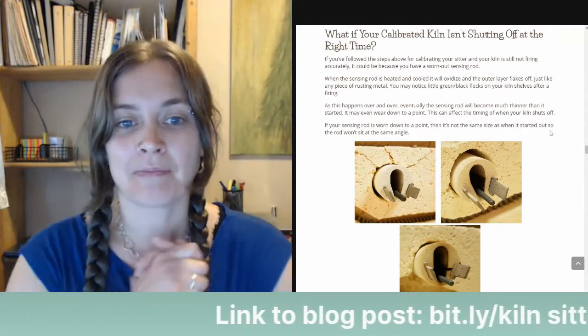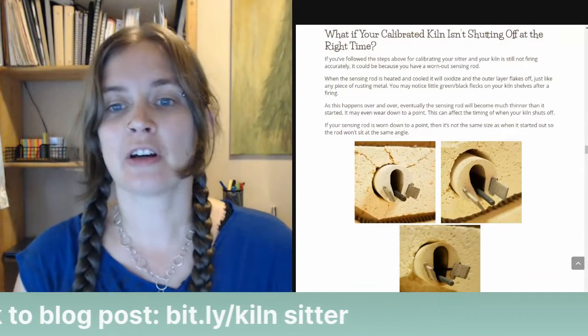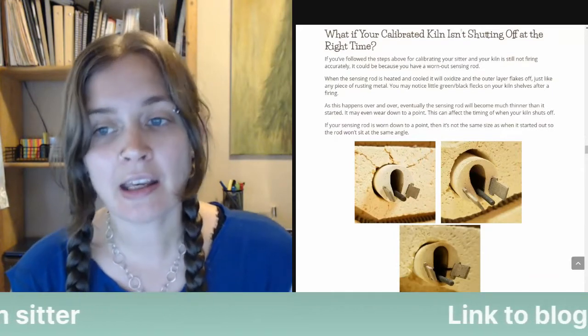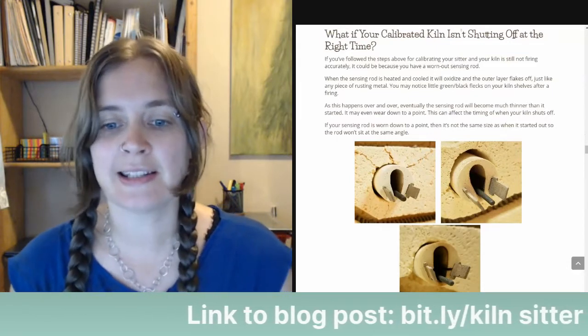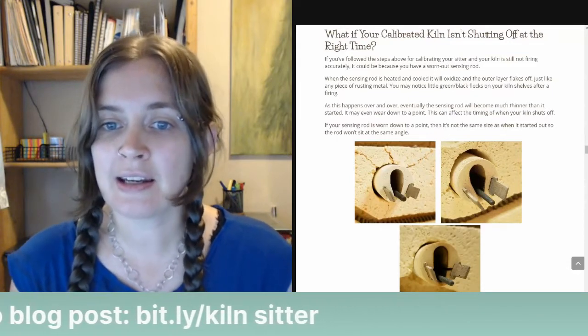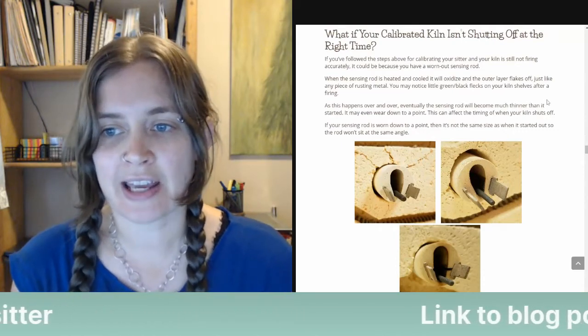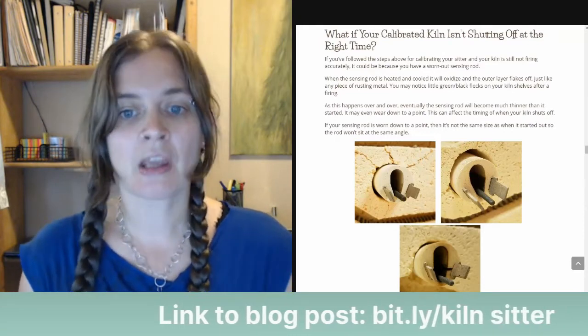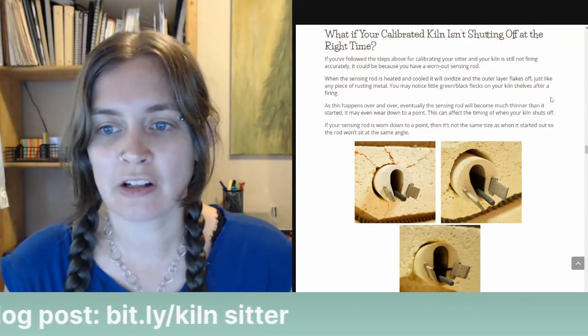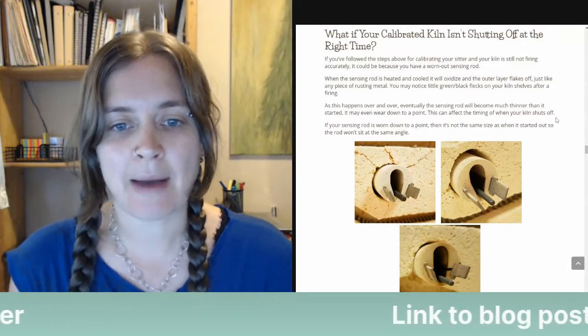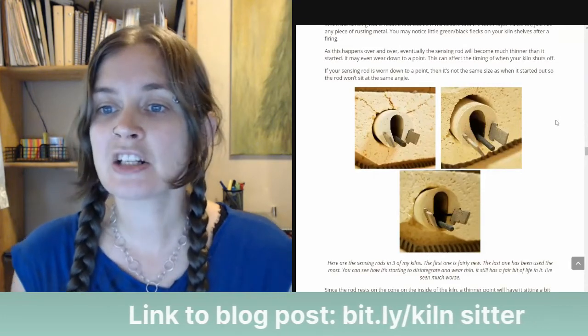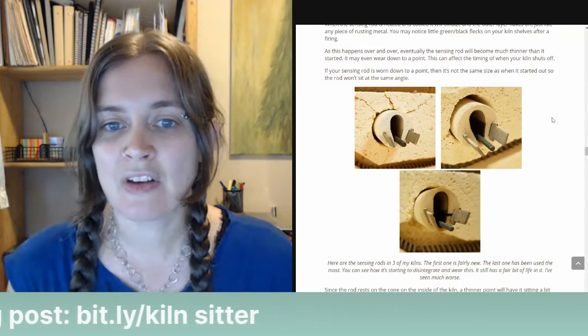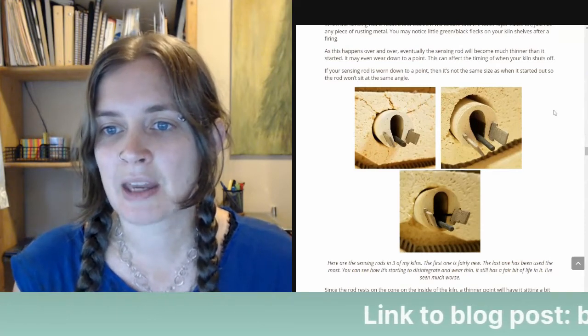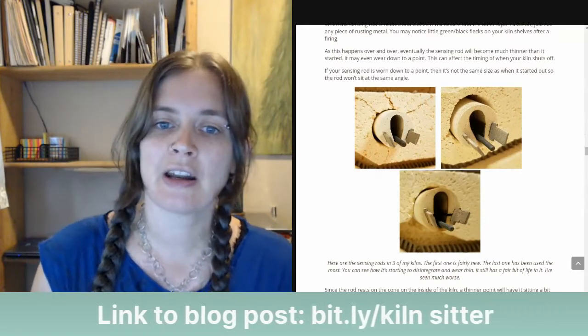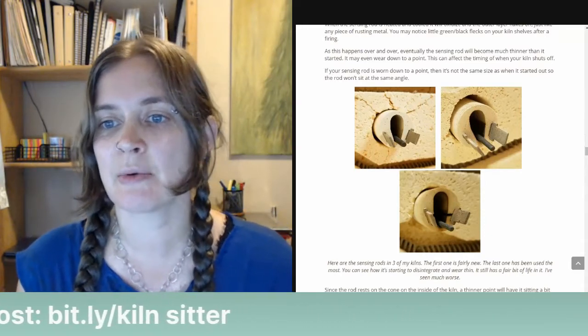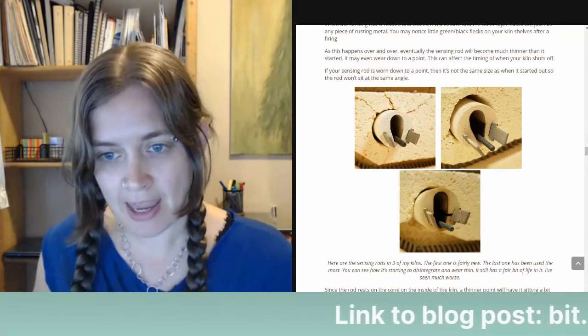Okay. So if you followed the steps above for calibrating your sitter and your kiln is still not firing accurately, it could be because you have a worn out sensing rod. When the sensing rod is heated and cooled, it will oxidize and the outer layer flakes off, just like any piece of rusting metal. You may notice little green or black flecks on your kiln shelves after a firing. As this happens over and over, eventually the sensing rod will become much thinner than when it started. It may even wear down to a point. This can affect the timing of when your kiln shuts off. If your sensing rod is worn down to a point, then it's not the same size as when it started, so the rod won't sit at the same angle.